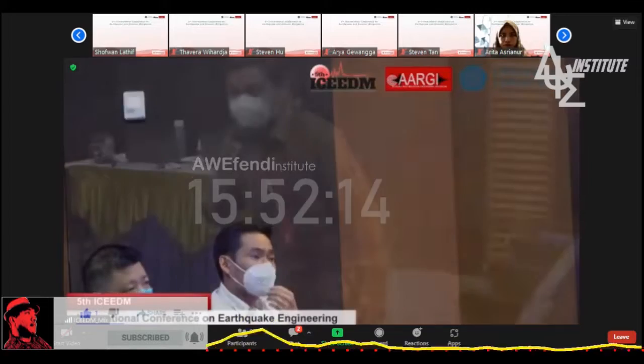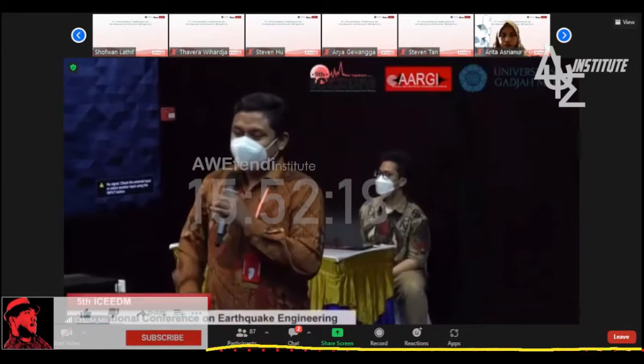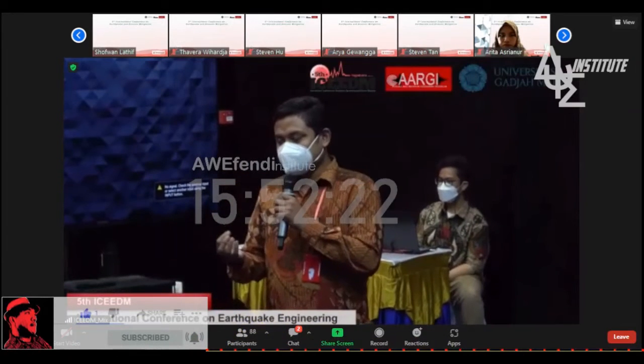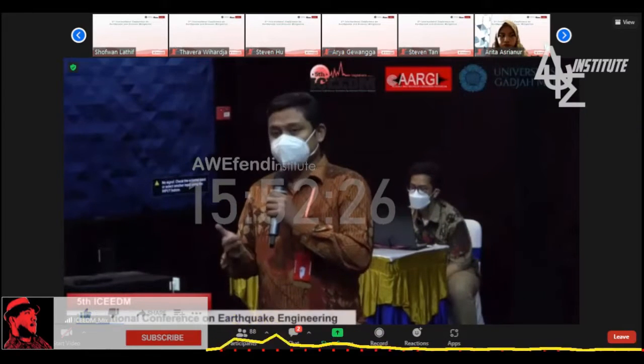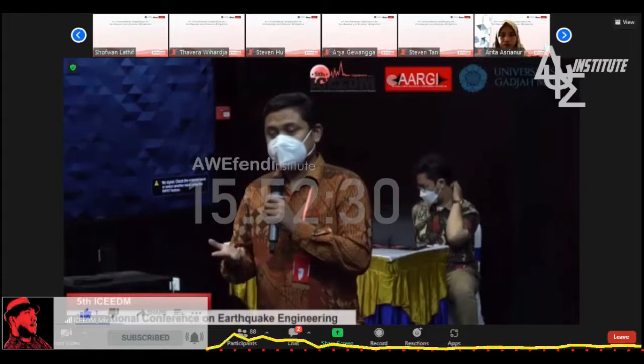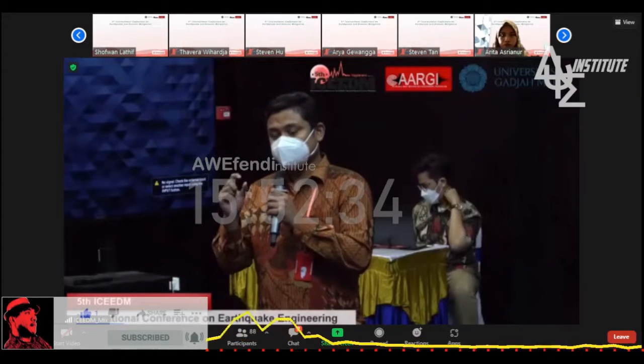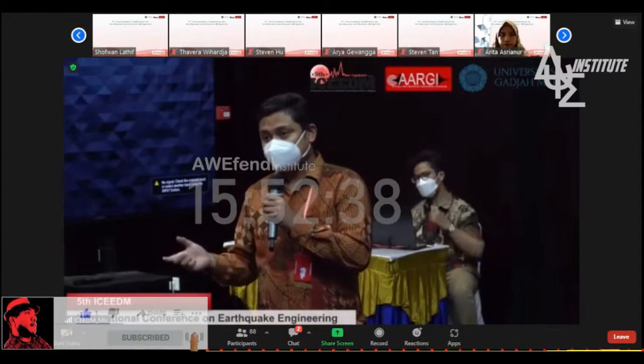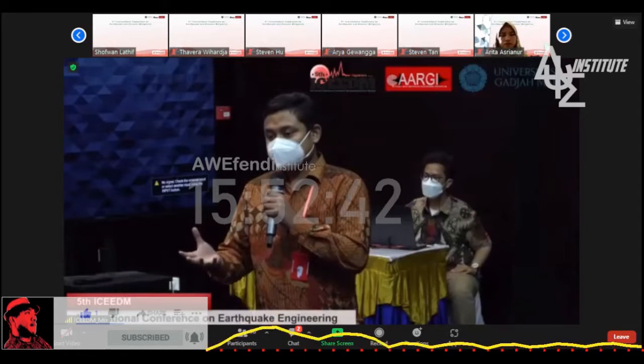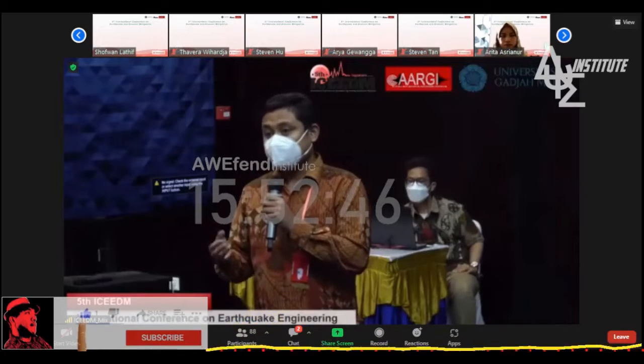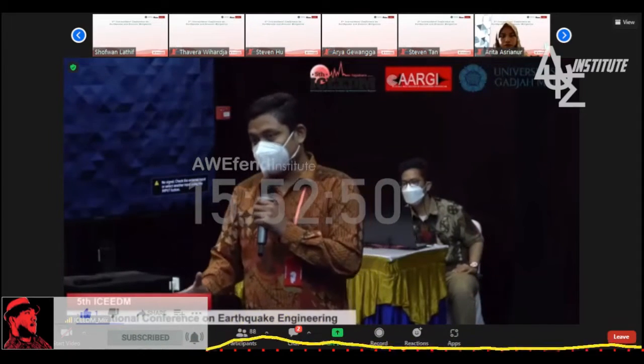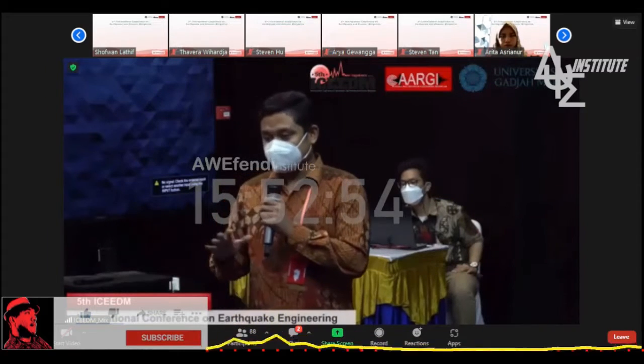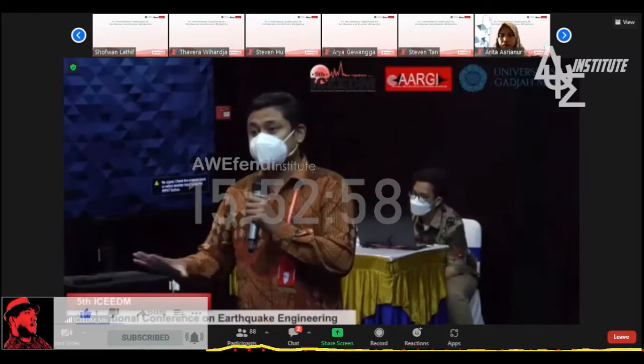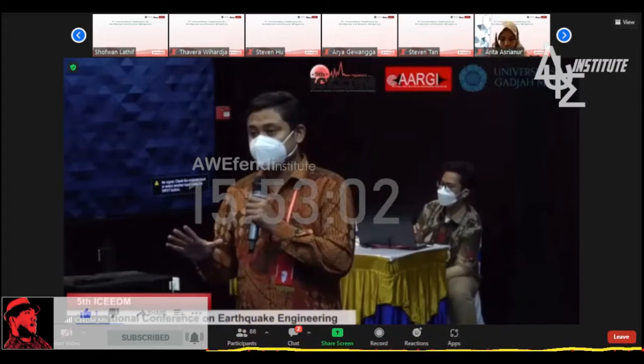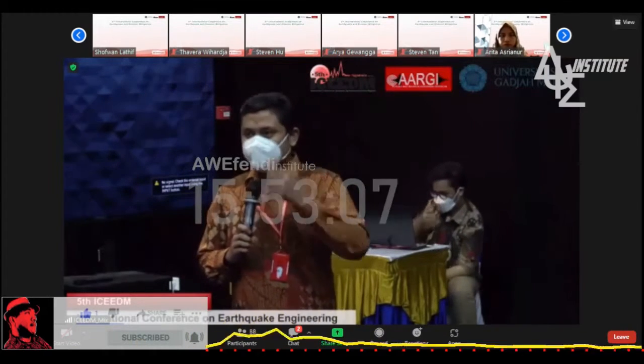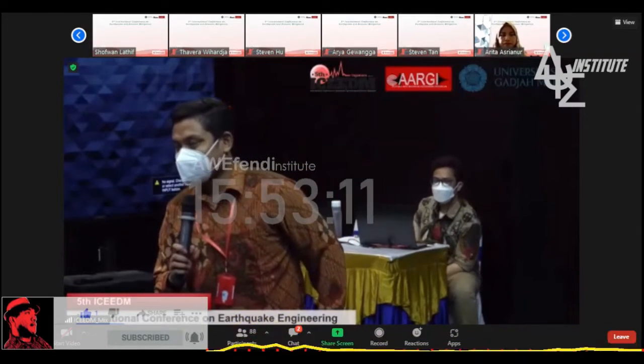Okay, regarding the mixture, we have cement, fly ash and fiber, and the fiber is quite small, typical of human hair, and we added 2% by volume. About the consistency or workability, it is more like SCC, so instead of using the slump test, we use slump flow. There's nothing more challenging about the dispersion of the fiber. It's quite easy compared to the SFRC that we fabricated. And what was your second question? Yes, my second question is related to the result.